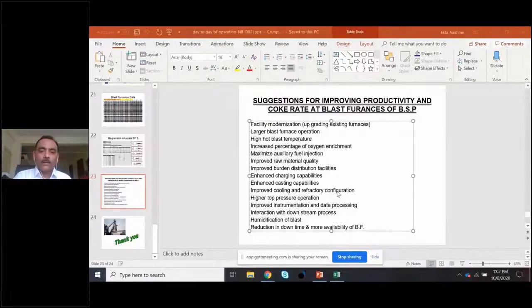It will chill the hearth. If water goes inside, the liquid will solidify. You will never be able to remove it. That is called chilling of the furnace. A very big threat for a blast furnace operator. Chilling hearth. So improved cooling and refractory configuration, higher hot top pressure operation.